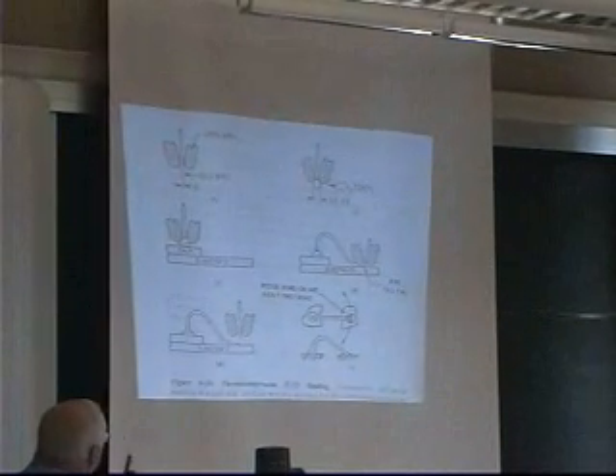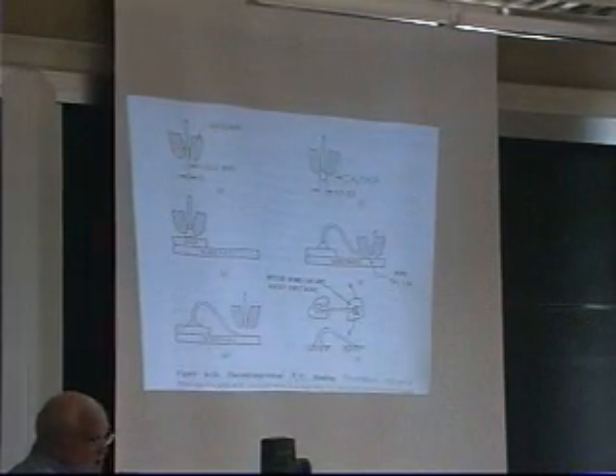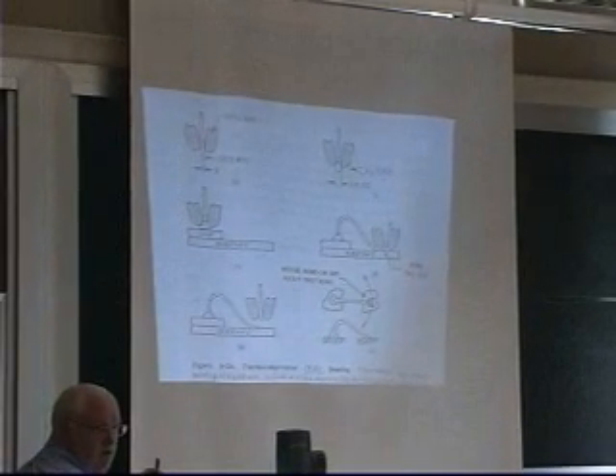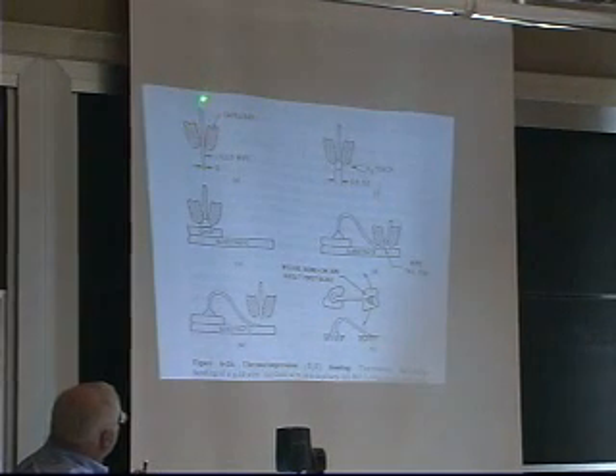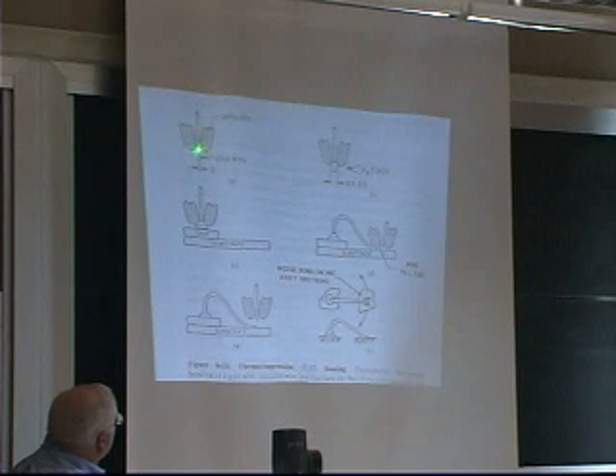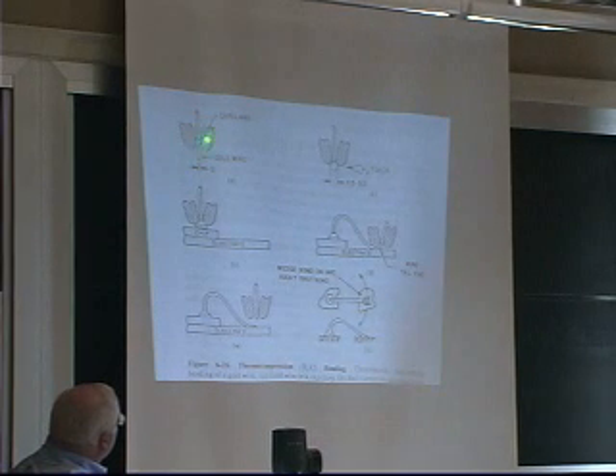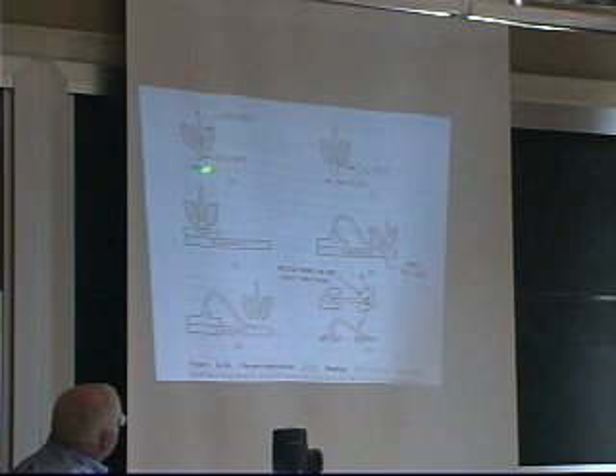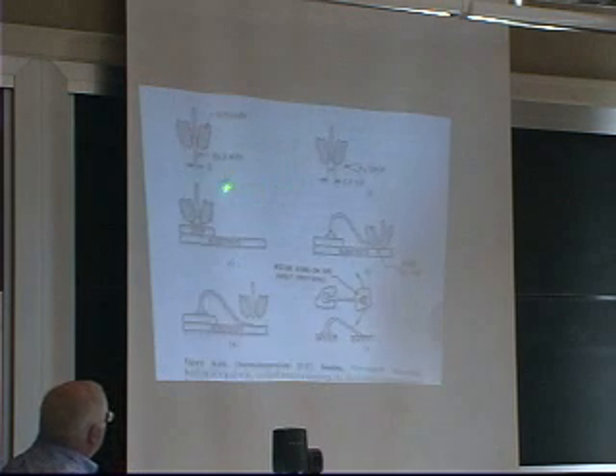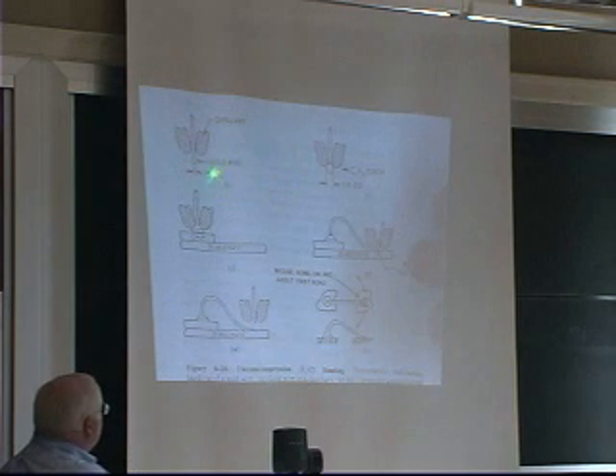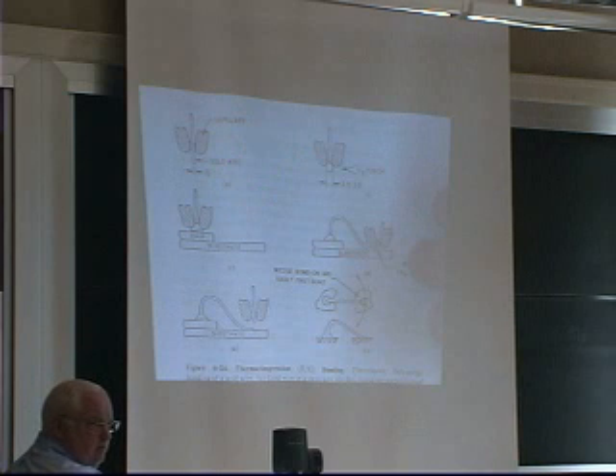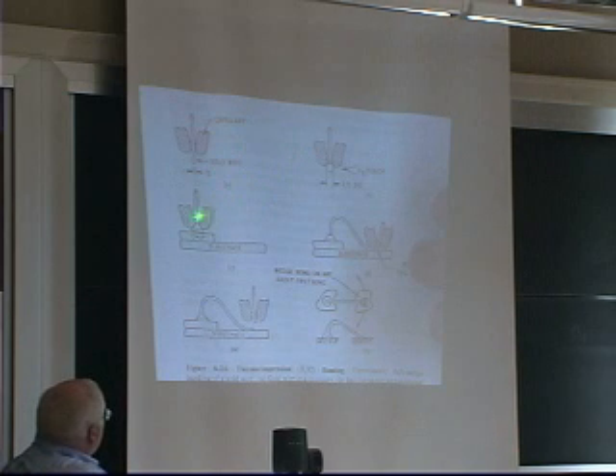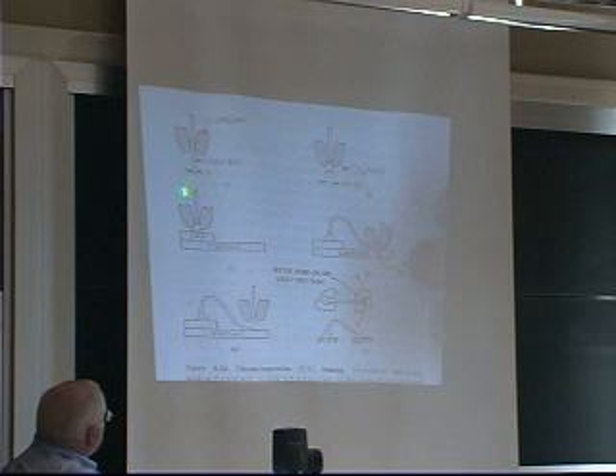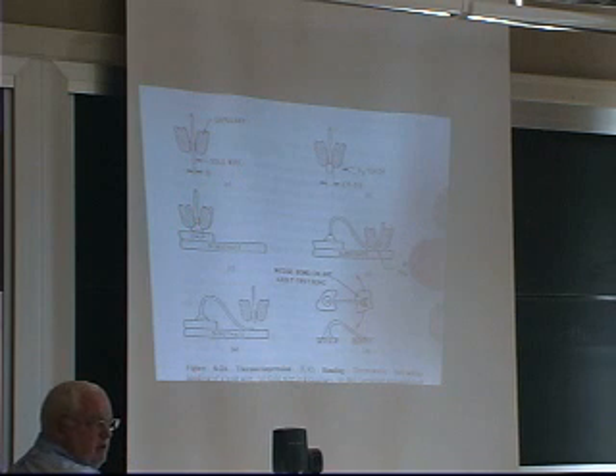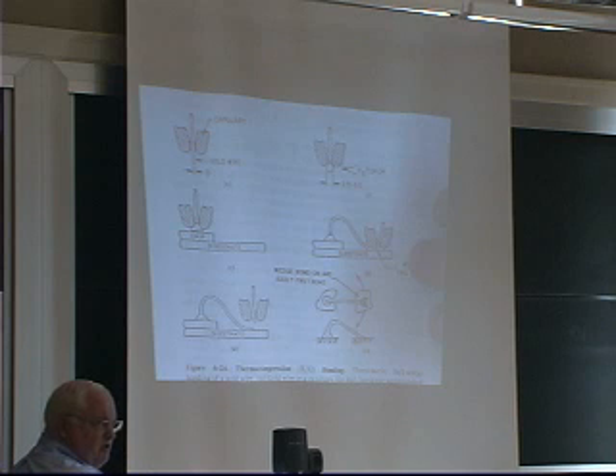Basically, I have a little sewing machine. It looks like a $50,000 sewing machine, because that's basically what it is. And rather than a cloth thread or a nylon thread, you have a little head that you feed a wire through, typically gold wire, about 1/1000th of an inch in diameter. 1/1000th of an inch is 25 microns. Standard size right now is 20 to 25 microns, so 8/10,000ths of an inch or so. And you just slam it into the surface, and they do this about 7 to 10 times a second. So when this thing's going, it's going faster than a sewing machine.